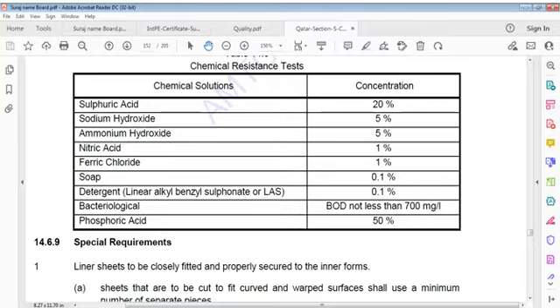Bacteriological biochemical oxygen demand not less than 700 milligram per liter. Phosphoric acid 50%. This is chemical resistance. That's a very important one. Sulfuric acid 20%, sodium hydroxide 5%, ammonium hydroxide 5%, nitric acid 1%, ferric chloride 1%, soap 0.1%, and detergent linear alkyl benzene sulfonate 0.1%, bacteriological BOD not less than 700 milligram per liter, and phosphoric acid 50%.